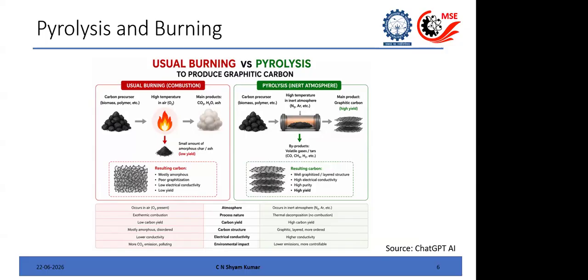And if you have a precursor material with aromatic structure, these structures can freeze and form the building blocks for sp2 carbon. Because if you remember the aromatic ring, if you remove all the other volatiles and other things, then the carbon ring will freeze, and these carbon rings are the building blocks for the sp2 carbon. So basically, you have more sp2 content. Because of that, you have enhanced conductivity. And since it is sp2, you will have a layered structure.